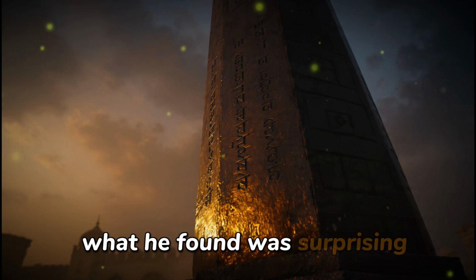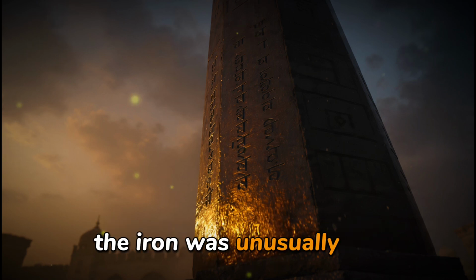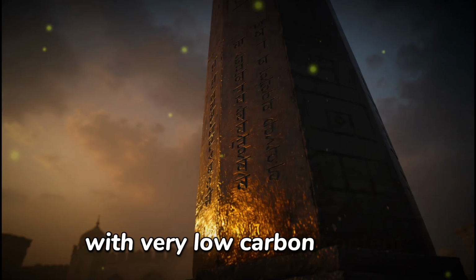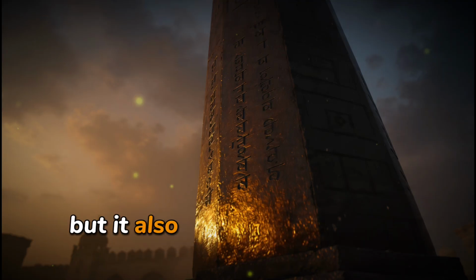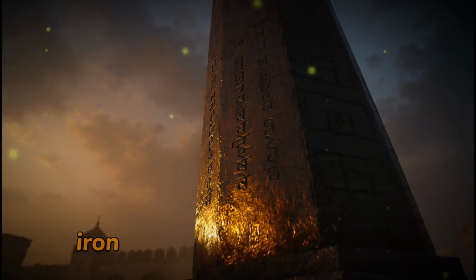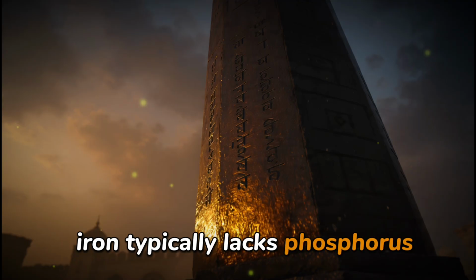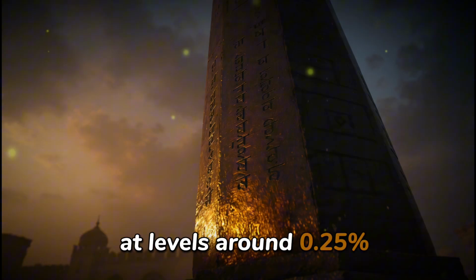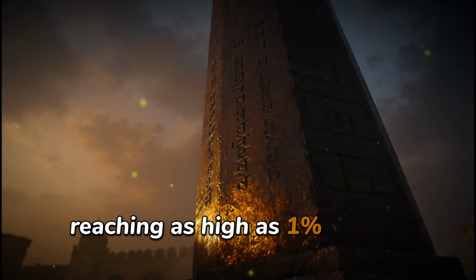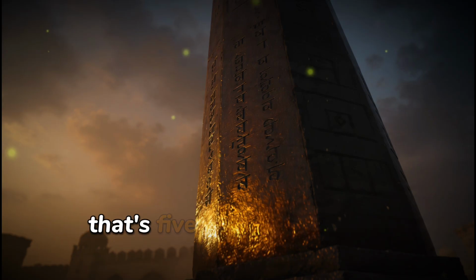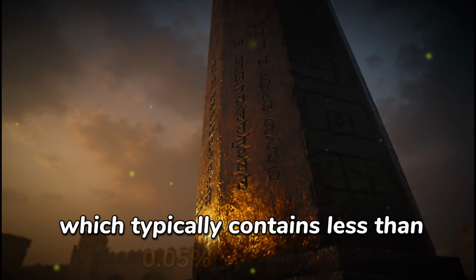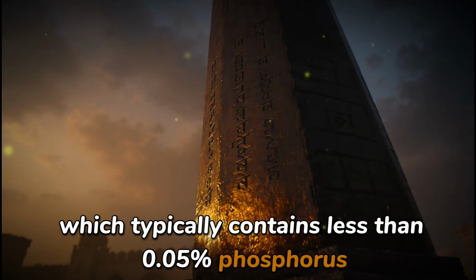What he found was surprising. The iron was unusually pure, with very low carbon content. But it also contained something unusual. The iron contained phosphorus at levels around 0.25%, reaching as high as 1% in some samples. That's 5 times higher than modern iron produced in blast furnaces, which typically contains less than 0.05% phosphorus.